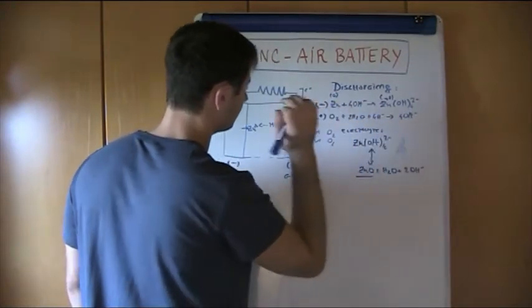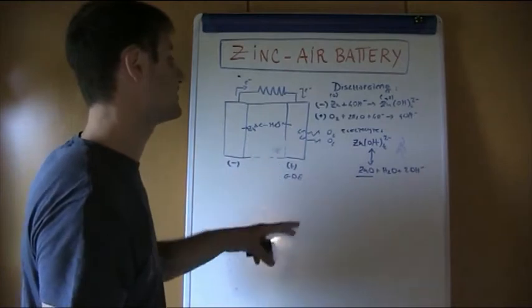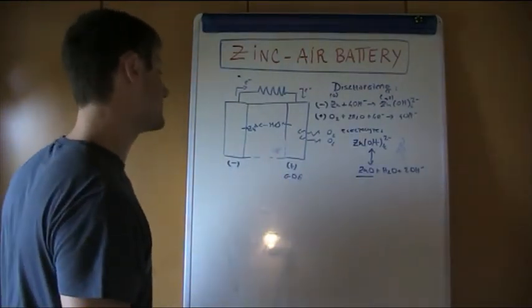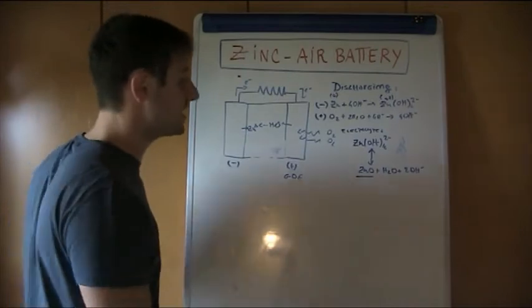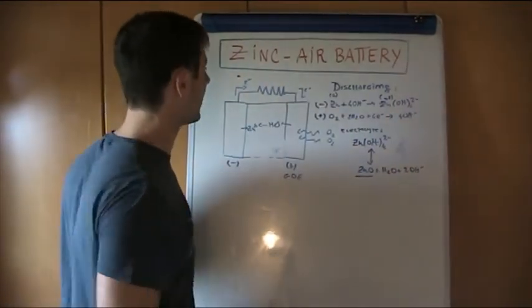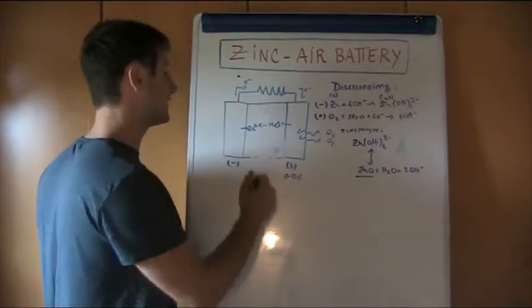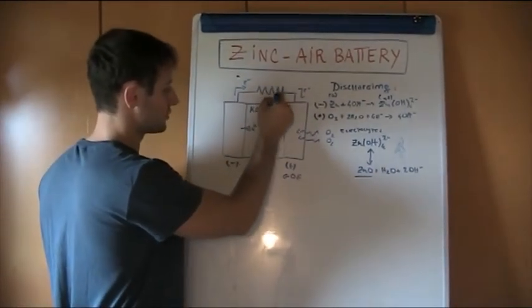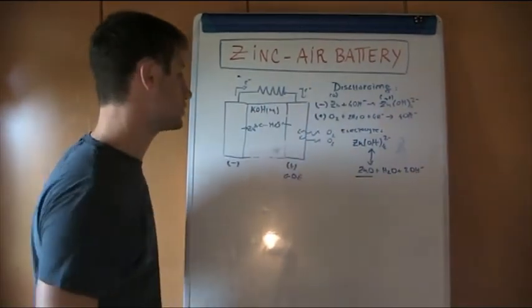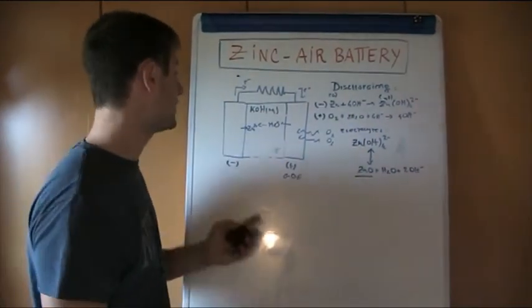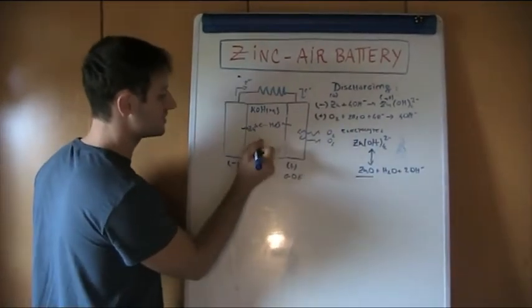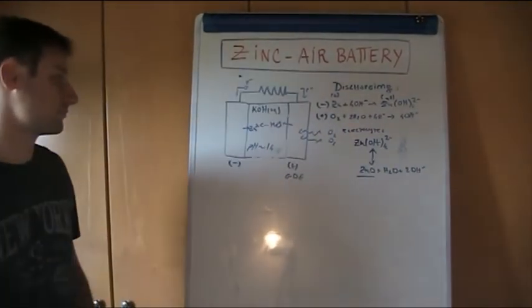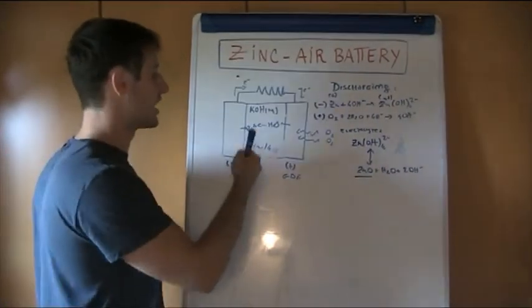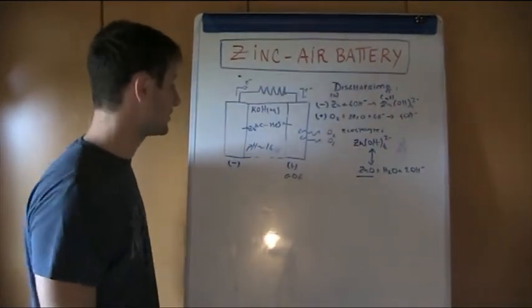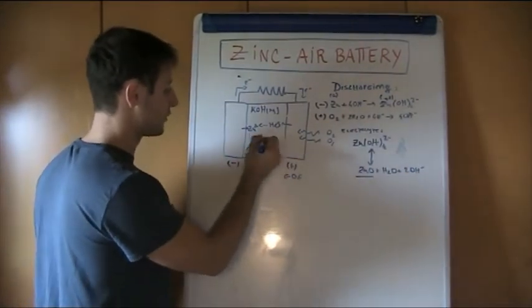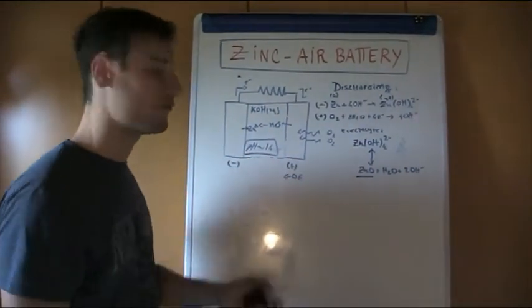In a Zinc-Air battery, we have these types of reaction. And it's important also to describe what the electrolyte is. So in general, the state of the art for Zinc-Air battery describes an electrolyte that is an alkaline solution. So we have KOH in an aqueous medium, in order to ensure a pH value that is around 14. So basically we need to introduce a solution of potassium hydroxide in order to ensure this value of pH. And we will see why this value of pH is crucial.